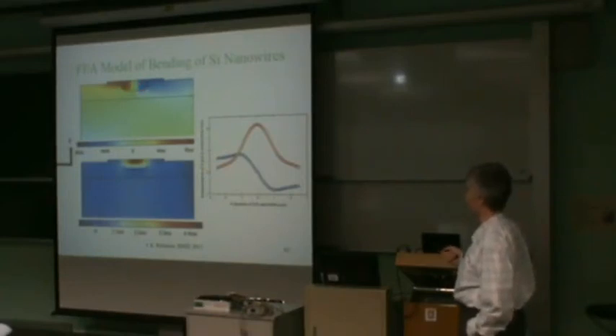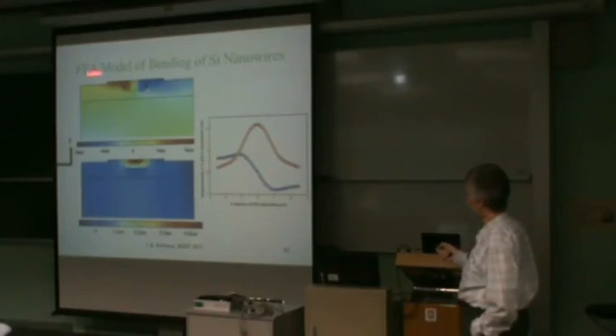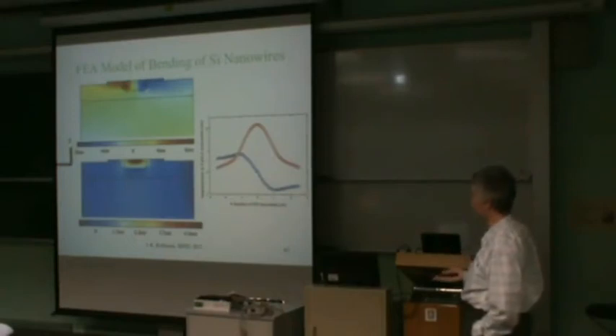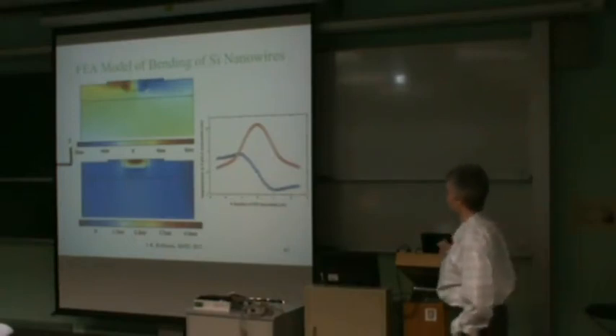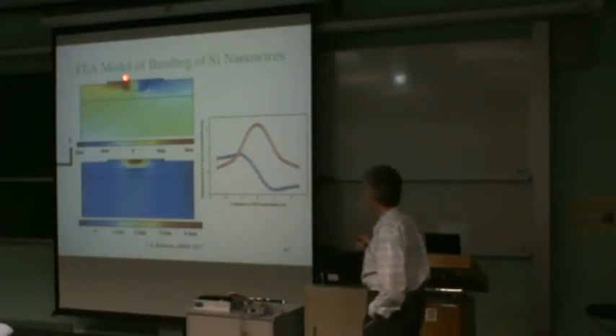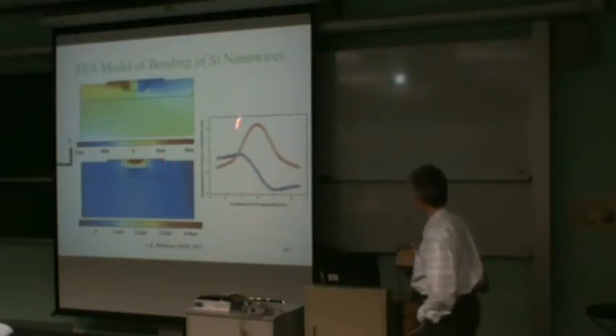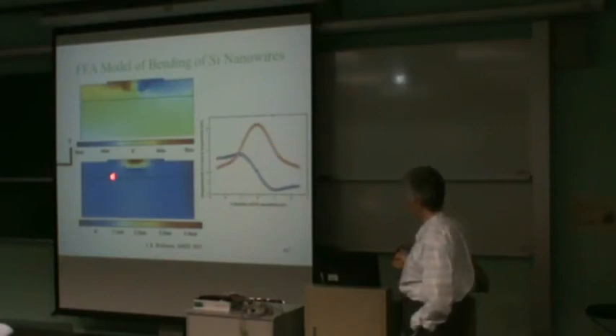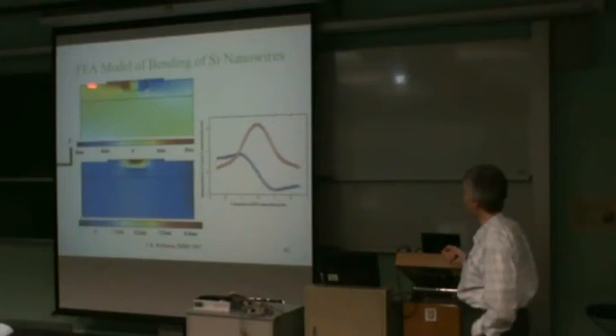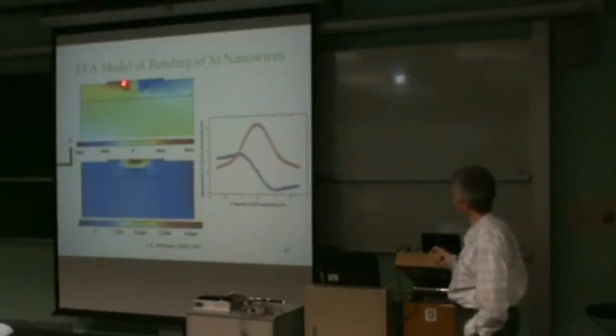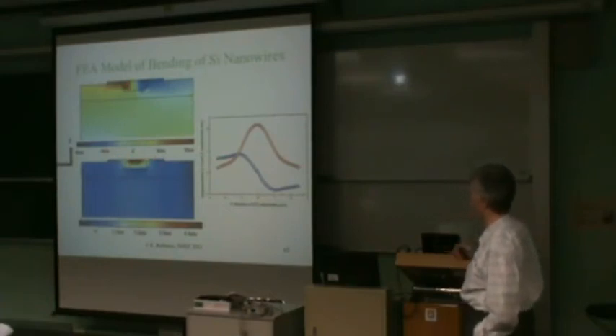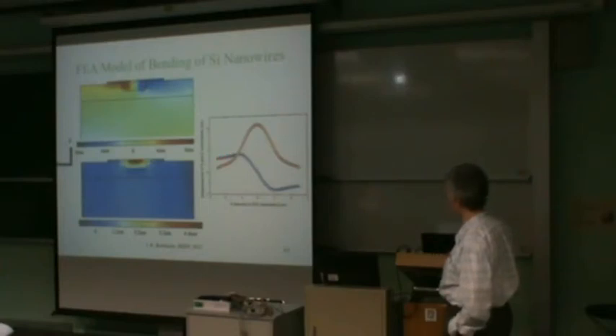What we did was just model what we thought was happening, which is we put a piece of silicon on top of a piece of SiO2 and then a silicon handle underneath. And inside this box region here, we put a Gaussian-shaped stress profile and increased the value of the stress that appears inside that box. And what happens is that this is the Z component, the vertical component of the distortion. The middle moves upwards and makes a sort of bridge-like picture. That's shown in red over here. That's the height of the sample for the value of the stress that we've applied. And in the sideways direction, you get a sort of dipole where it responds to the mechanical distortion of the bending of the beam with a left and right motion that's shown in the blue curve over here.